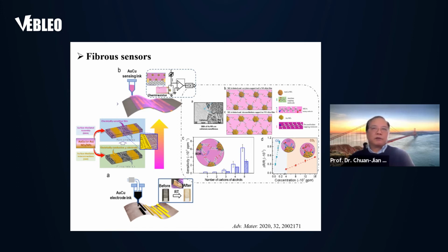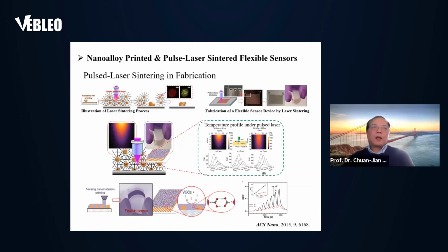One particular thing I want to emphasize is that the fiber sensor is very, very sensitive. You can also do things like this. The nice thing about room temperature sintering is you can use a paper substrate, because conventional sintering is all at high temperature, more than 100 degrees, and now the paper can survive that kind of temperature.